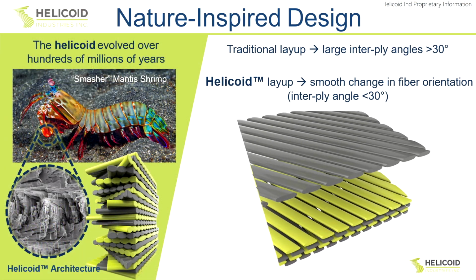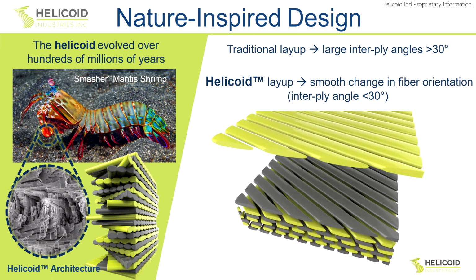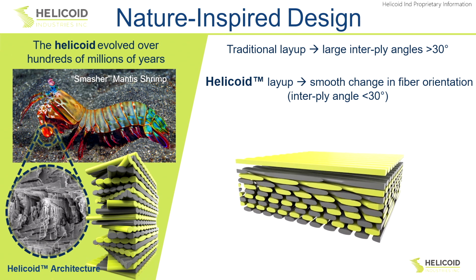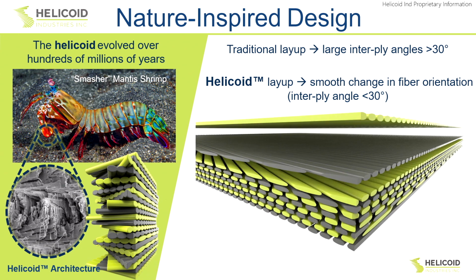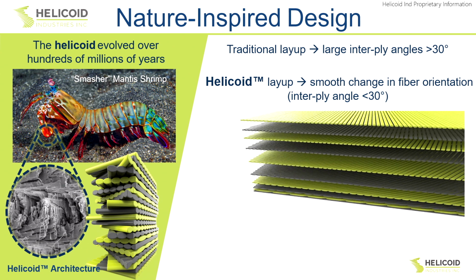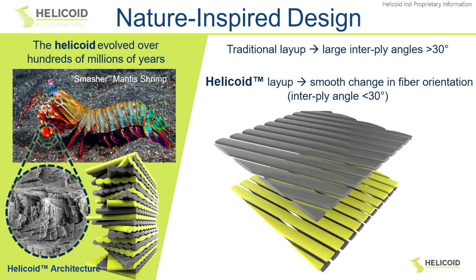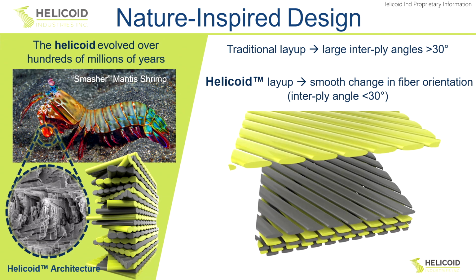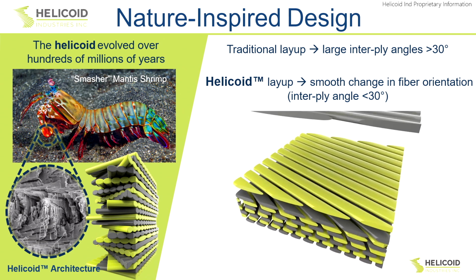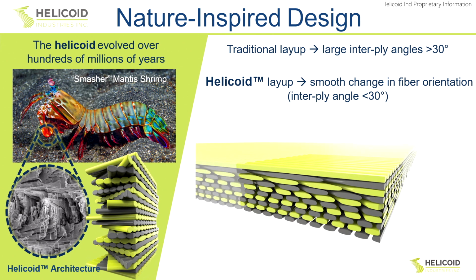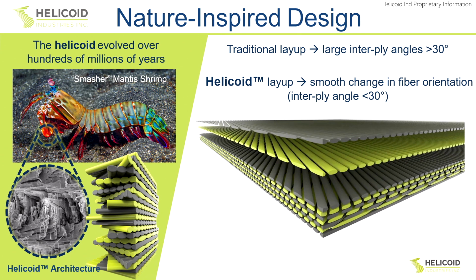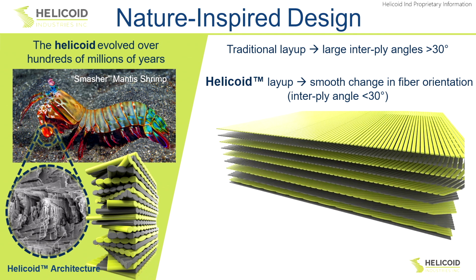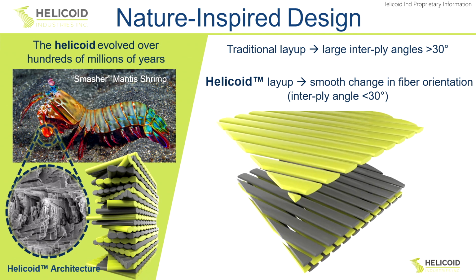And in this helicoid design, what you have is a smoothening of the change in fiber orientation across multiple plies, and this is where the abstraction takes place. So our intention is not to mimic directly the microstructure of the club, because there you have a change in fiber orientation between 1 degree and 2 degrees, which is not feasible at all in any industrial application. But to understand what that smoothening of change of fiber orientation brings in terms of mechanical performance, stress distribution, fracture mechanics. So that's where the research has gone for most of it.